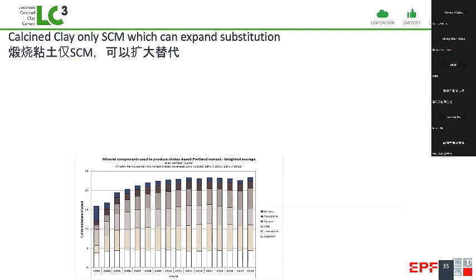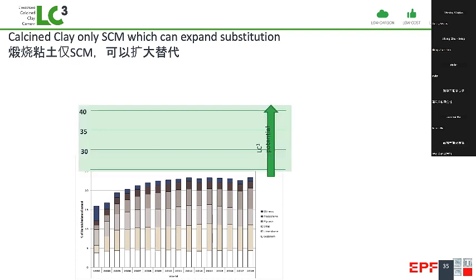This graph here shows the average level of substitution around the world. And you can see in the last 10 to 15 years, this has stagnated at only around 20%. This is due to the limitation on the availability of slag and fly ash. If we remove this limitation, which is very easy to do by the abundant availability of calcined clay, we can easily imagine going to an average substitution level of, for example, 40%. On a world scale, this would represent a saving of 400 million tons of CO2 per year.